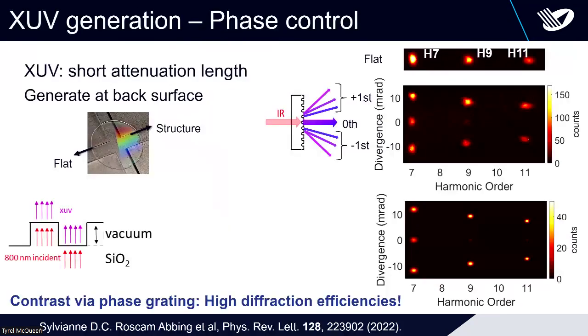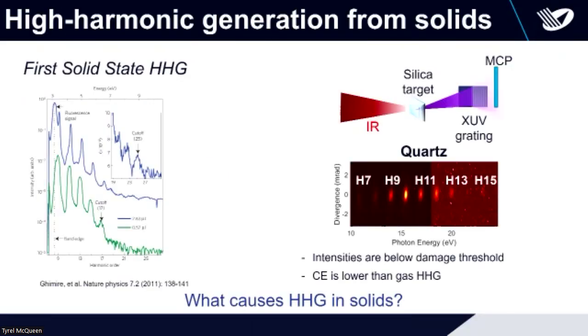Yeah, so we also did several experiments now. Let's maybe start here, where we generate harmonics directly from solids. Interestingly, it was 1988 that someone discovered this high harmonic generation from gases, and then it took until 2011 and someone tried to put a solid in the laser beam, and it also worked. But the energies that come out are not that high. So in that case, the first demonstration, people managed to generate harmonics up to about 100 nanometer.